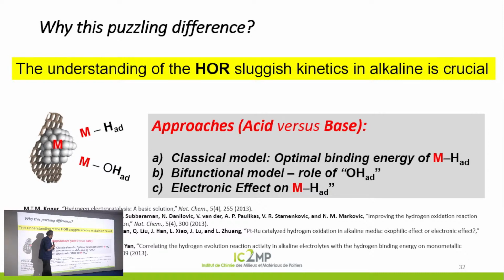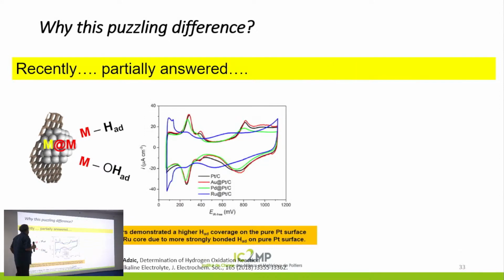We know that with the classical model we have an optimal binding. That means we have the metal with the hydrogen adsorbed. We can also have the bifunctional model as I showed with the sp2 domains. But if there is an electronic effect, this bond energy should change. All right. And this appears to occur in this system. So in order to convince you of that, I hope that you understand this cyclic voltammetry curve. That is in alkaline, here is the hydrogen region, and here is the oxide region. The important thing is this peak. This peak actually reveals the presence of OH.